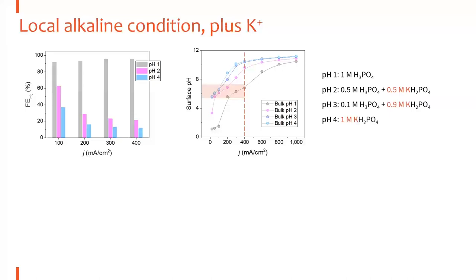So why do we have local alkaline conditions, but no CO2 reduction? We look at the recipe of our electrolyte. How we prepare the pH 1, 2, 3, 4 electrolytes is that we mix phosphoric acid with a certain amount of dihydrogen phosphate salt. For pH 2, we have 0.5 molar potassium dihydrogen phosphate. For pH 3, we have 0.9 molar. For pH 4, we have 1 molar.